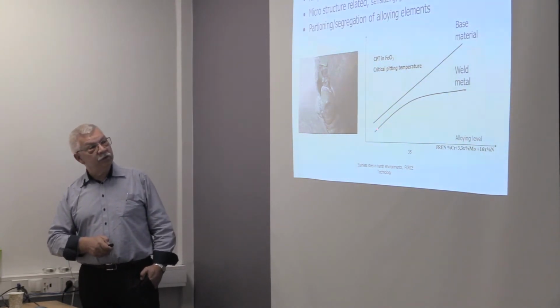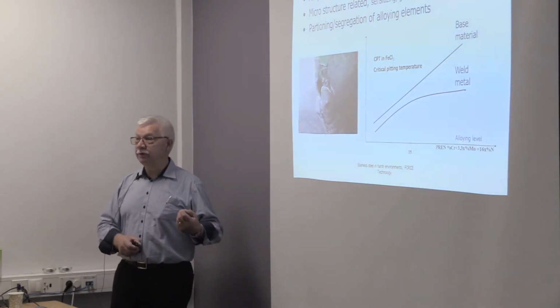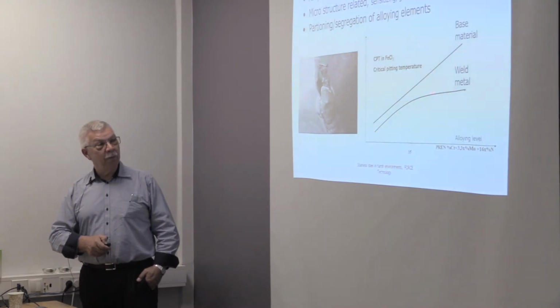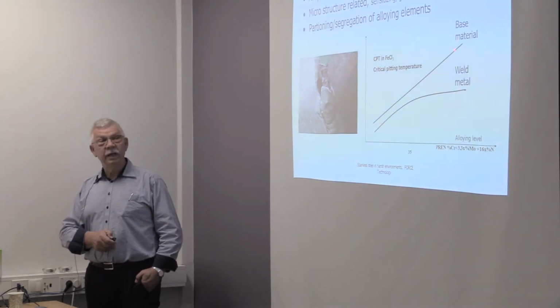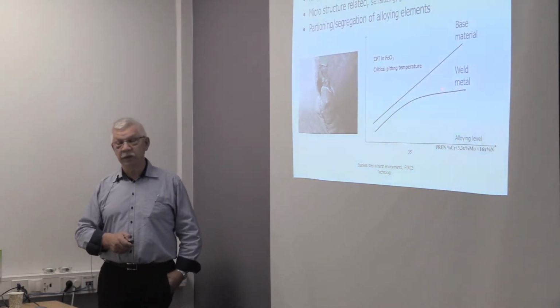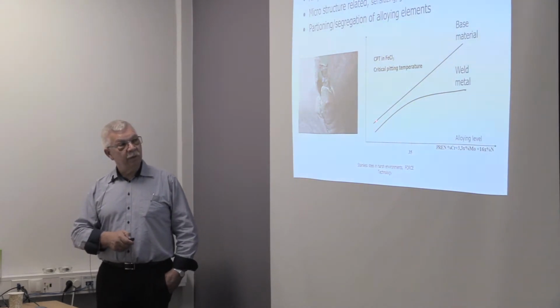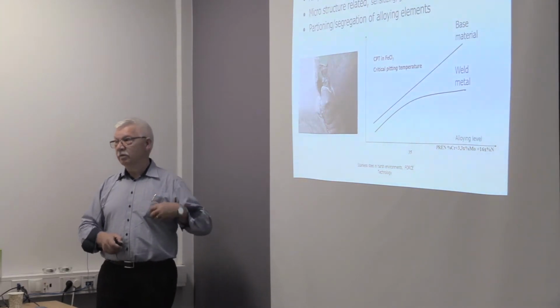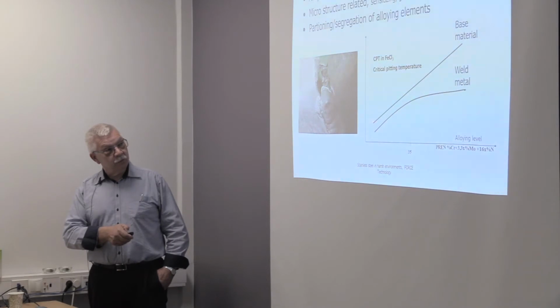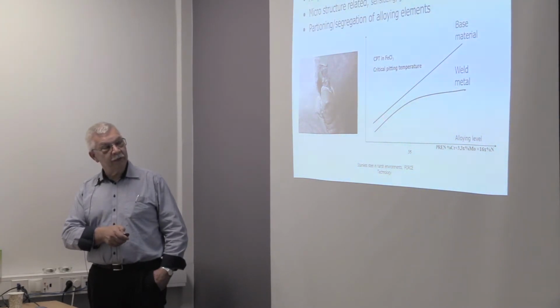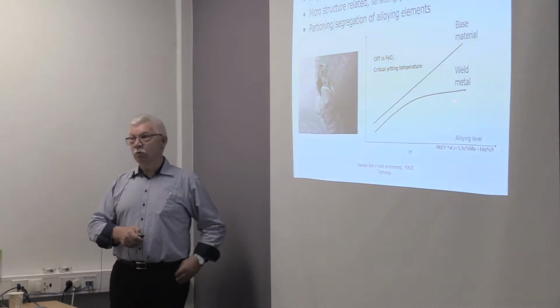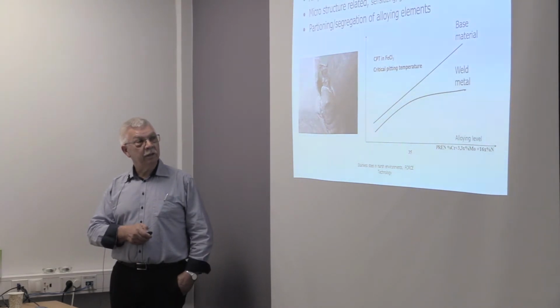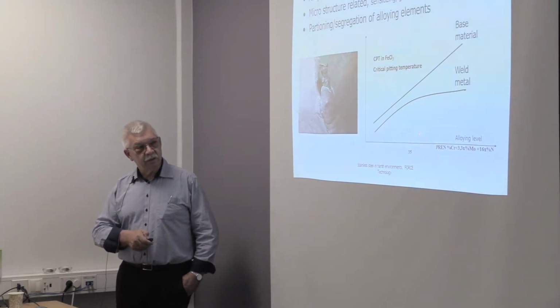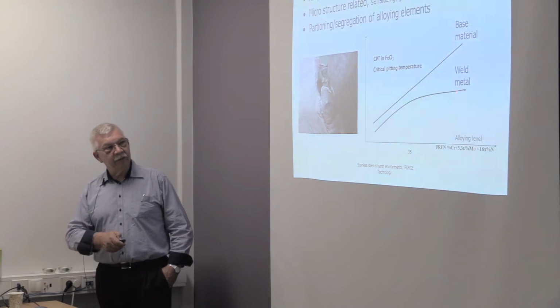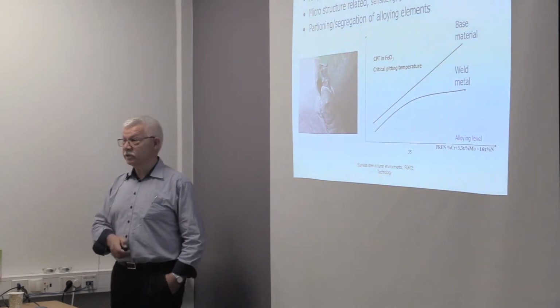But as you can see, if we do the same with weld metal, and this is autogenous welding, that is without filler, then we can see that it will definitely be lower. And at some point, it will have a very large deviation from the base material. And again, that is due to the partitioning of the alloying elements. The distance here might be larger or smaller. If we have very fast welding, fast cooling, then the distance will be low. The weld metal will be very close to the base material. But with more heat and larger pools, we will have a variation. This is larger. But from here, which is almost like the 904L, above that we cannot have welds which match the base material resistance.